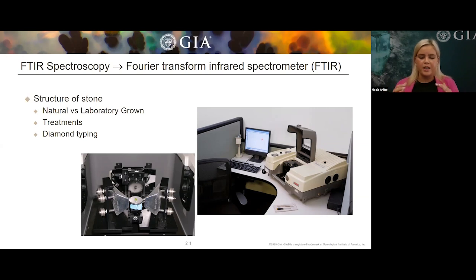Okay, so when we use FTIR, again, we're going to be looking at that structural component of the stone, and that can help us with calls such as natural or laboratory grown. And we use that for emeralds and chrysoberyls. We can use it to help see if a stone has been treated. So for jadeite and turquoise, we can look for polymer peaks. We can use it to assist with heat or no heat calls in some of our corundum. I can show you that.